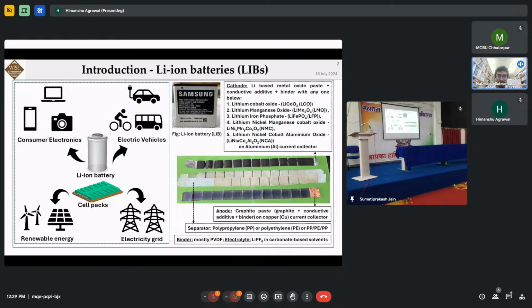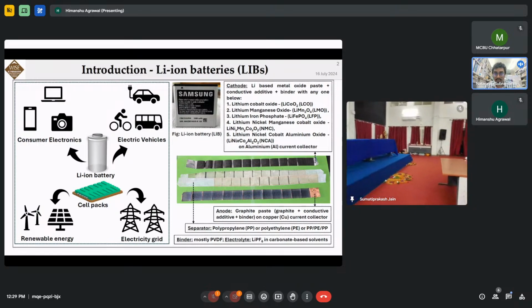Its demand increases every year. So we know that a lithium-ion battery is composed of cathode, anode, electrolyte, and separator. The cathode is mainly lithium-based metal oxide with conductive additive and binder, made into a slurry and pasted on the aluminum current collector foil. As you can see from this figure, the lithium-based metal oxide is either lithium cobalt oxide, lithium manganese oxide, lithium iron phosphate, lithium nickel manganese cobalt oxide, or lithium nickel cobalt aluminum oxide on the aluminum current collector.